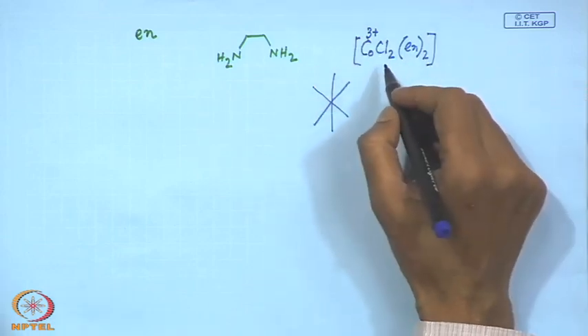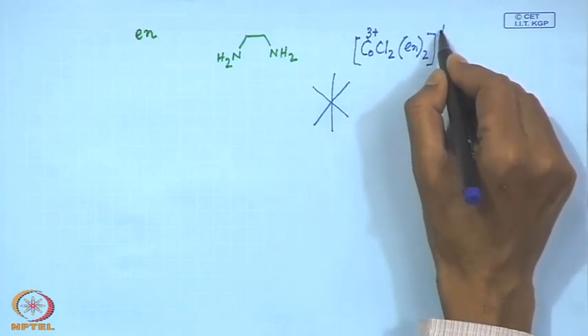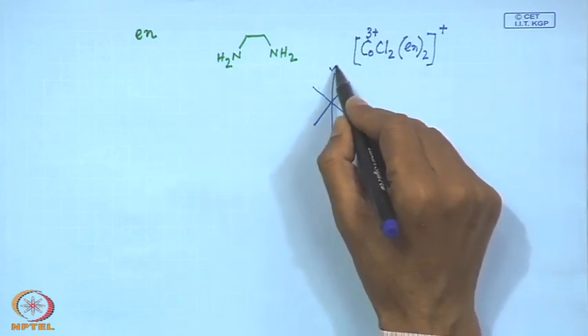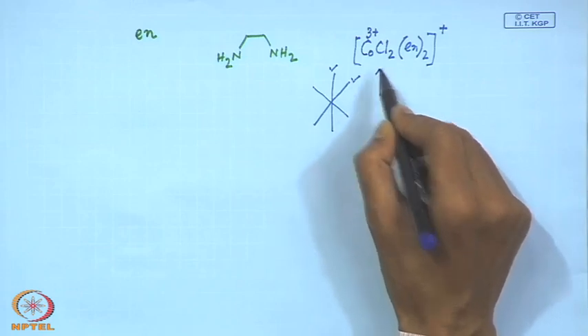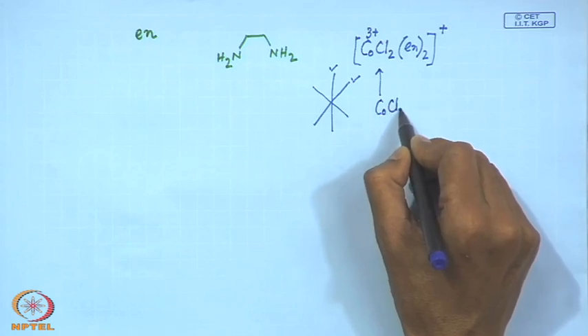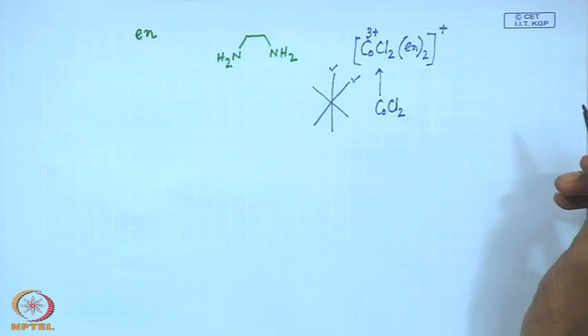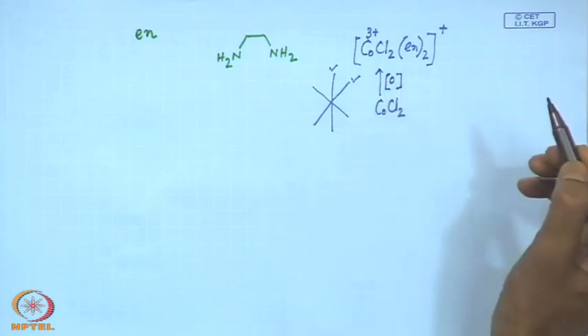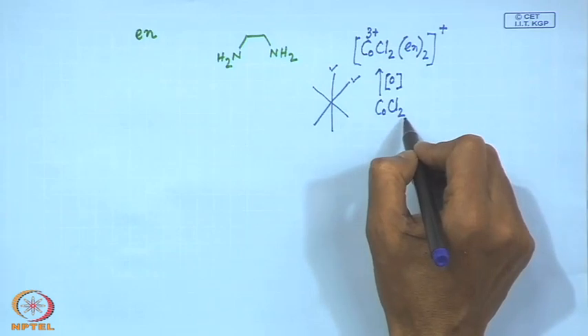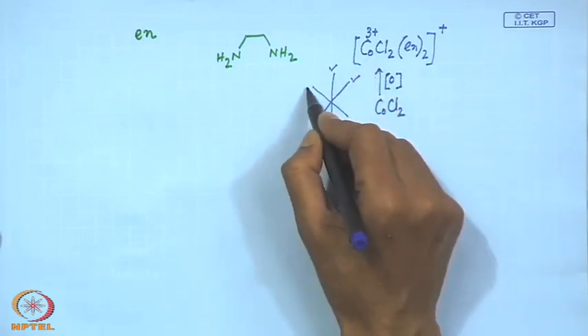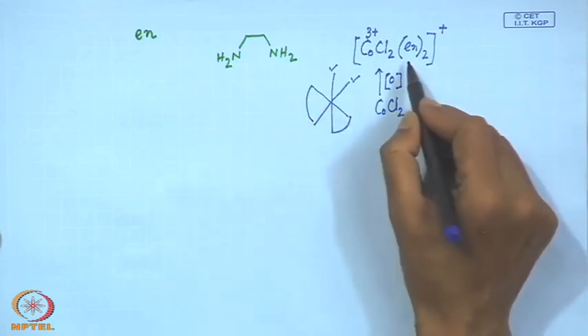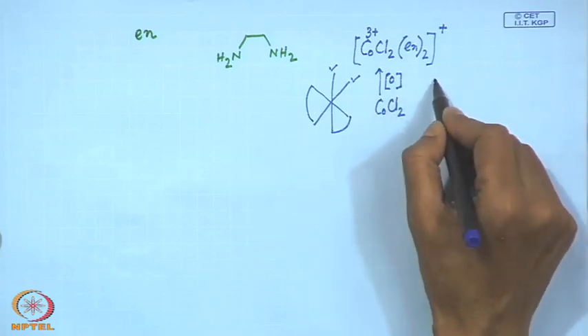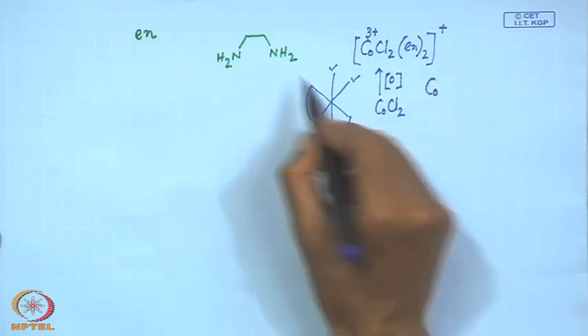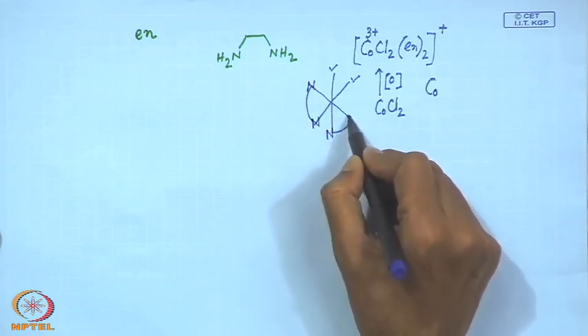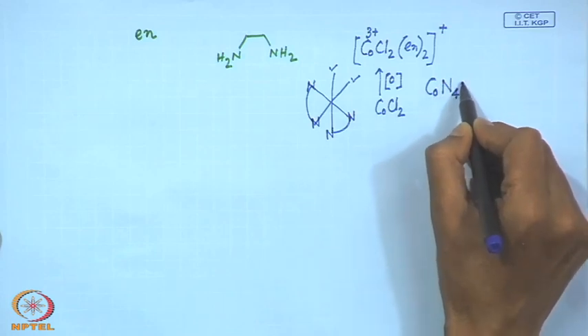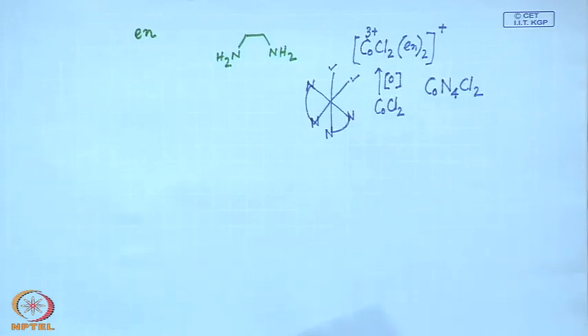we can go for the corresponding charge balance by 2 Cl-. So the overall charge of this complex would be again plus, and two of these positions are occupied by Cl, which in most cases can come from the starting metal salt used for the synthesis of the compound, that means cobaltous chloride, cobalt 2 chloride, with some oxidation by passing air or hydrogen peroxide. So two of these chlorides are still present with the cobalt, and two more positions are occupied by these two bidentate ligands of ethylene diamine. So we get a typical octahedral compound where the cobalt is bound to 6 atoms, 4 of them coming from the nitrogens of ethylene diamine. So it is CoN4, and 2 of them are Cl2, so CoN4Cl2.